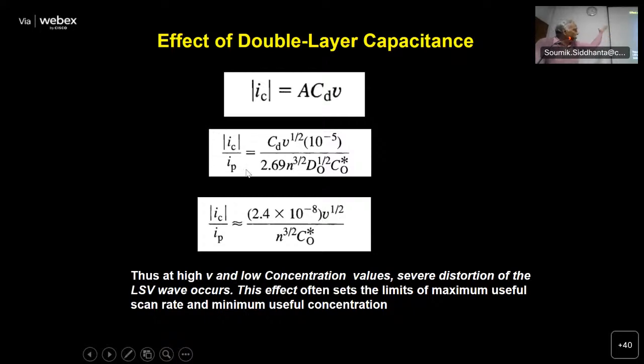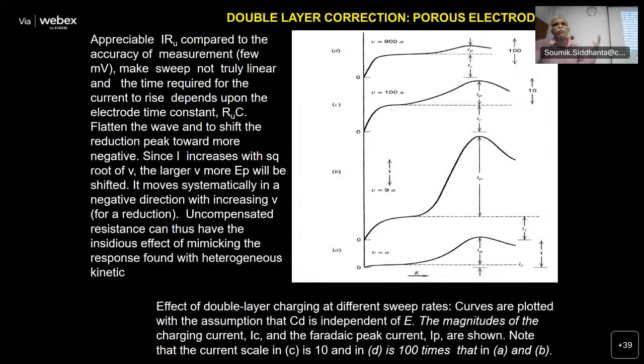So the ratio of noise to signal. Signal is Faradaic current, Ip, peak current. Ic is the noise. Noise to signal depends on these parameters. Nu power half, and noise to signal or charging current to the Faradaic current or peak current, you can calculate as a function of nu power half. So at high scan rate and low concentration, several distortions happen in voltammograms. High scan rate and very low concentration. That is why biosensors, if you want to measure with parts per million, parts per billion, you will have difficulties of this, and hence people go to differential pulse voltammetry. Similarly, double layer correction, sometimes you can see in voltammogram. Here you see the signal is so small and the noise is so huge. So noise to signal ratio gets affected by these. This is essentially for porous electrodes.